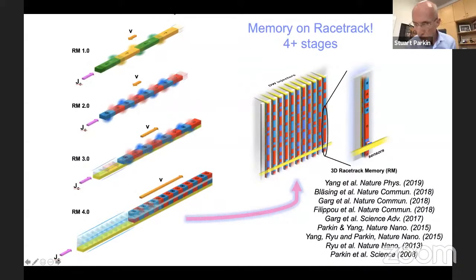Well, it turns out that in soft magnetic materials, because there's no anisotropy, the size of the domain walls is determined by magnetic exchange, Heisenberg exchange, and by dipole fields. And so these are relatively large domain walls, which are highly elastic. So Racetrack Memory 2.0 was rotating magnetization from in the plane to out of the plane by engineering thin film structures, and shrinking the size of the domain walls by more than 100 times, let's say from a few hundred nanometers to a few nanometers. And then it turns out, again, the domain walls moved at roughly the same velocity, again in the direction of the flow of spin angular momentum from internally scattered and created spin currents.